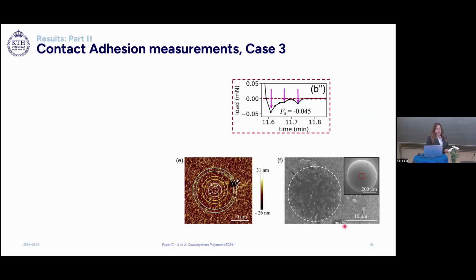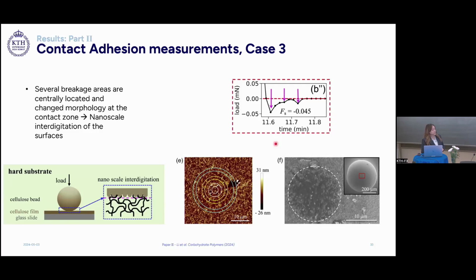The separation force happens gradually, and when we analyze the surfaces after separation on the film as well as the cellulose bead, we can see on SEM that the morphology of the surface is different, and we have several breakage areas centrally located on the surface of the film. And this suggests that there were nanoscale interdigitation of the surfaces.